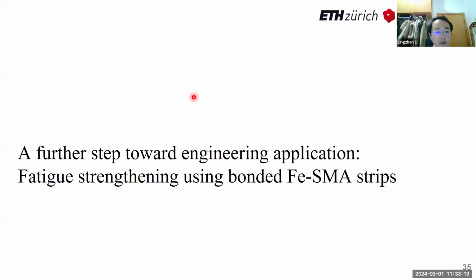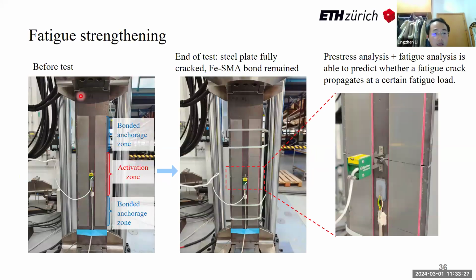I call it a pilot strengthening project: fatigue strengthening using bonded Fe-SMA strips. Here is a steel plate with a central through-thickness crack, which is hidden by this crack opening gauge. I used 4 shape memory alloy strips for strengthening each steel plate, 2 on the front side, 2 at the back side. At the center region, the memory alloy strips were heated to generate pre-stress, and 2 bonded anchorage zones remain unheated and transfer the pre-stress to the substrate.